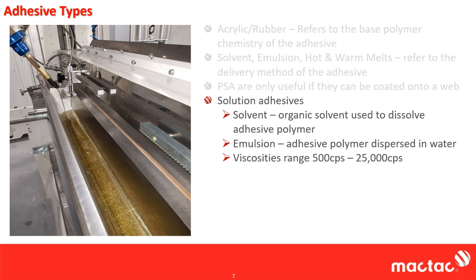These adhesives can range in viscosities from 500 centipoise to 25,000 centipoise. To give you an idea, water is 1 centipoise at room temperature. And so really the purpose here is that if you try to measure the viscosity of an adhesive that's already been cast out and cured, it'd be in the millions, maybe tens of millions of centipoise. So we've got to find a way to get it onto the web.